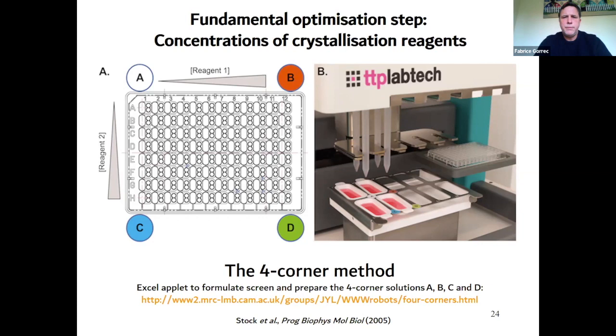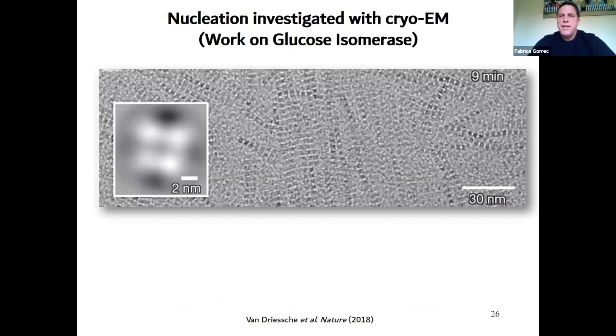Nucleation and growth. Interestingly, cryo-EM is giving us more clues about nucleation, which is the rate limiting step. So we can see that there's already quite a high level of order straight away. During nucleation, it's only a few macromolecules that form the cluster that we can see there.